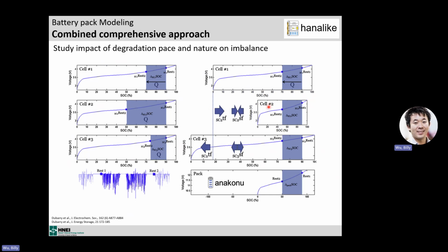But if you scale and translate the cells so that you match vertically the first 3 points and vertically the last 3 points, then it's true for every point. So it's a really simple approach. We just scale cells. Once we do that with 2 parameters, the translation factor and the scaling factor, we can sum every point and get the pack response for any point. By playing with those 2 parameters, we can simulate possible imbalance. And obviously, with those OCV curves, we can change the degradation, the cell-to-cell variations, and all of that. It's an extremely simple model, extremely efficient at replicating the impact of imbalance.